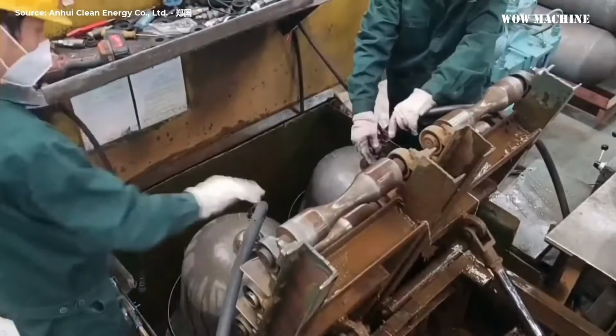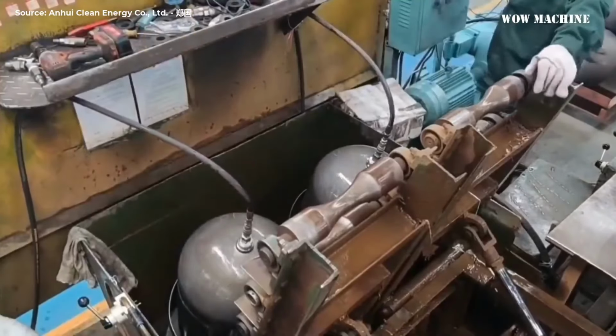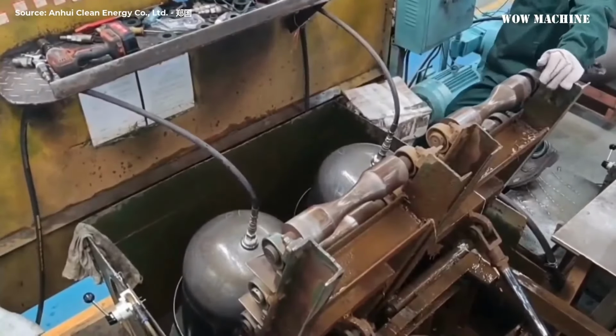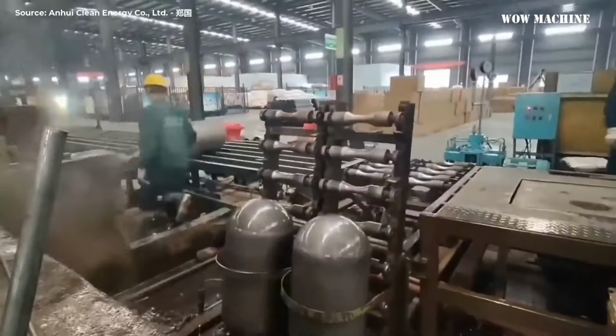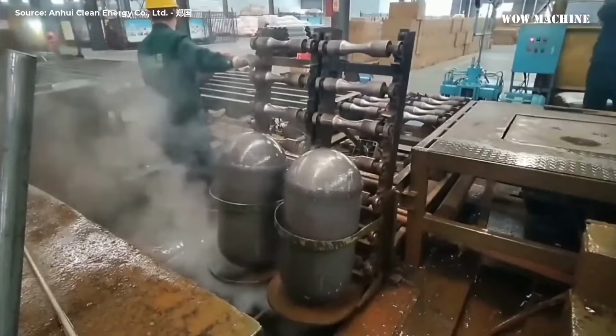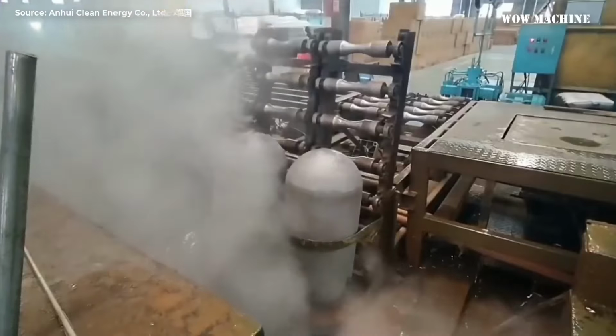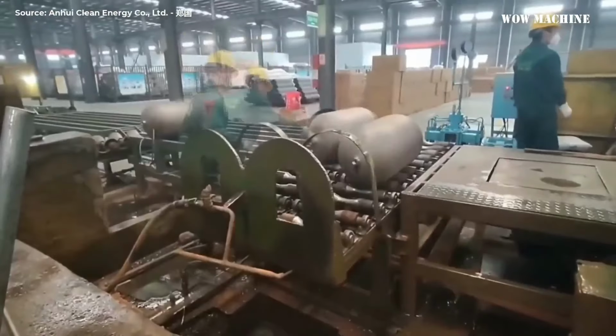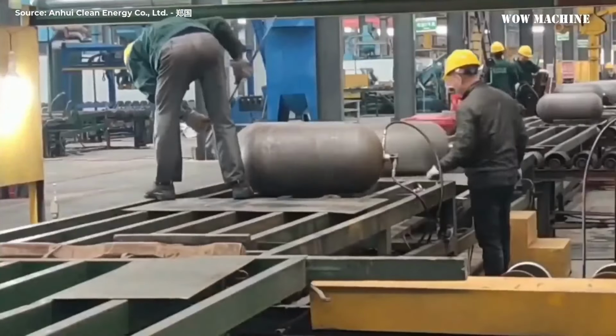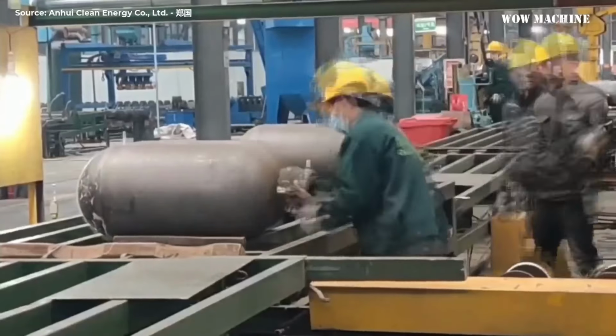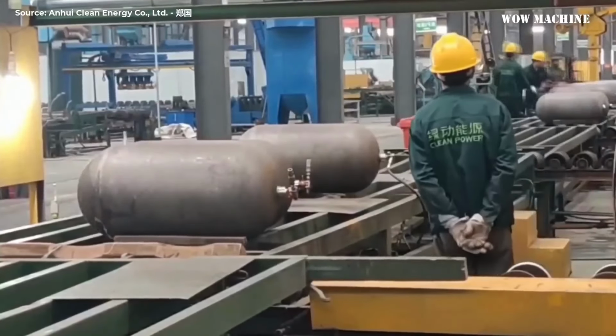Hydrostatic testing. This test involves filling the cylinder with water and pressurizing it to a level that exceeds the maximum allowable working pressure of the cylinder. The cylinder is then inspected for any leaks or defects that may have developed during the manufacturing process.